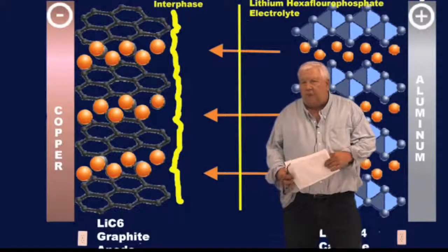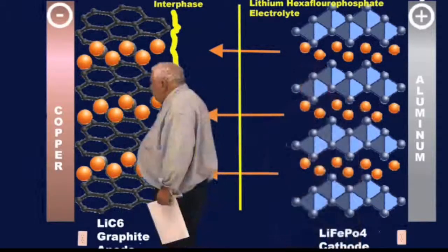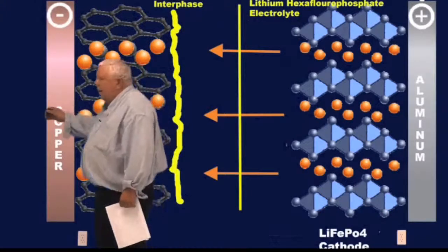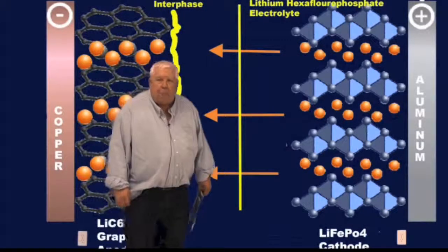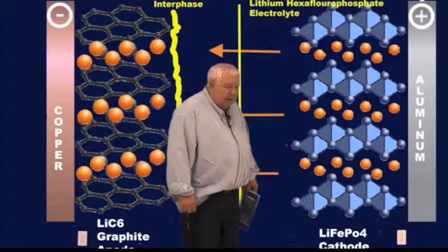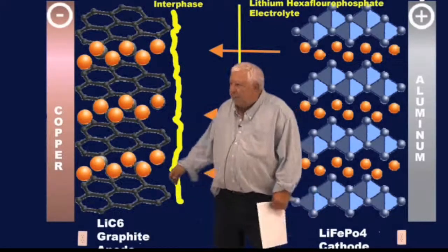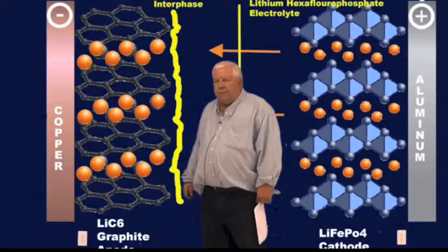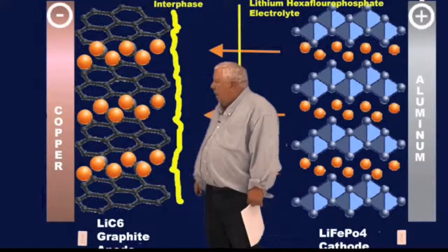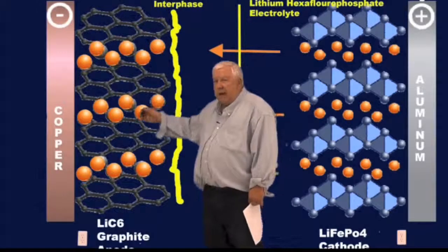This starts to occur below 1 volt. The copper begins to oxidize and essentially dissolve and give off copper ions into our battery cell. And that copper plating, every place that appears, reduces our ability, copper plating on that SEI layer.